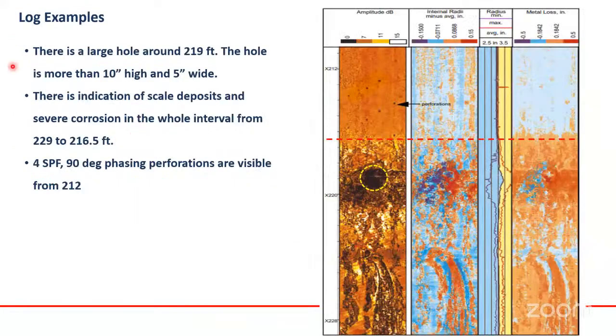This is another log example. There is a large hole around 219 feet. This one, a big hole. The hole is more than 10 inches high and 5 wide. There is an indication of scale deposits and severe corrosion in the whole interval. Okay, this is severe corrosion, as you see here. And also, as you see, we have 4 shots per foot perforation here.